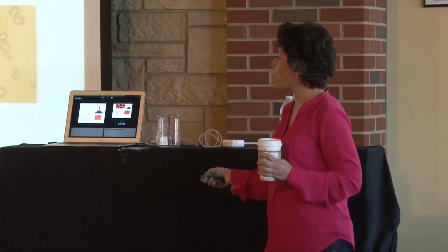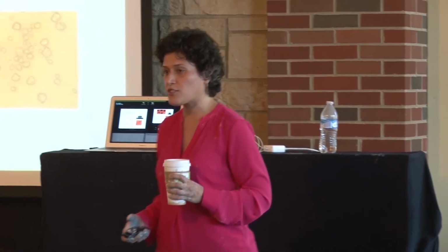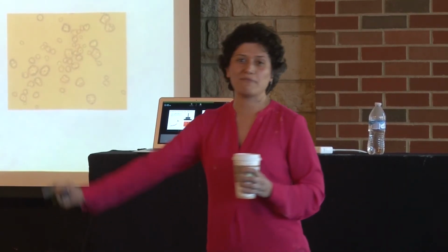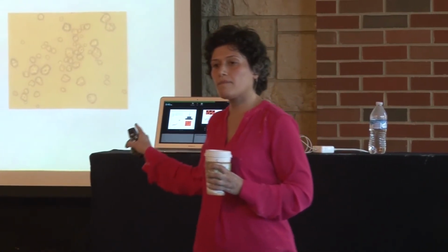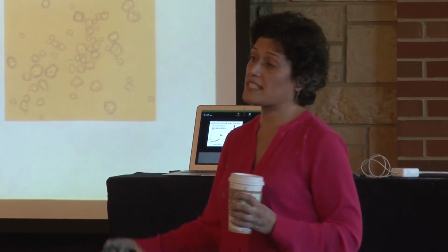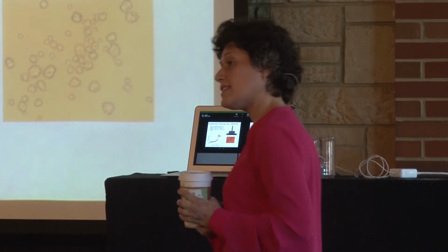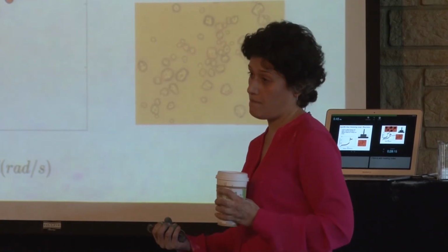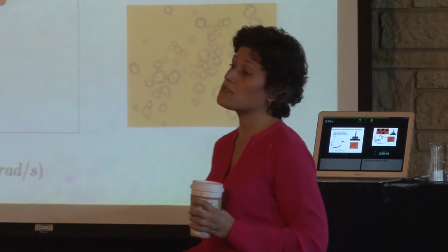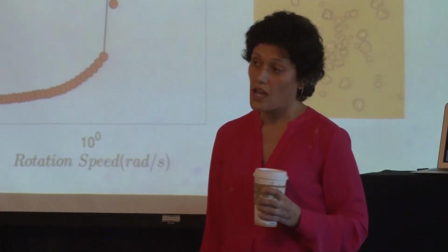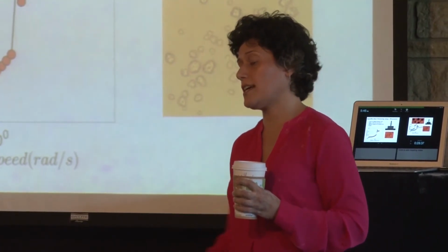And the first question, the point is that I didn't go into detail, and to be honest, it's perhaps the first presentation of my life without a single equation in it. My students from the mathematics course know that. There are two types of shear thickening behavior: continuous shear thickening and discontinuous shear thickening. What I'm presenting here is discontinuous shear thickening behavior. When you get to this regime, meaning that the volume fraction of solid is high in your system, you get this huge jump. Now, how can you reduce that? You have to reduce the volume fraction of the cornstarch in your water to go to continuous shear thickening, which is a slight increase in the torque. It's not discontinuous like that.